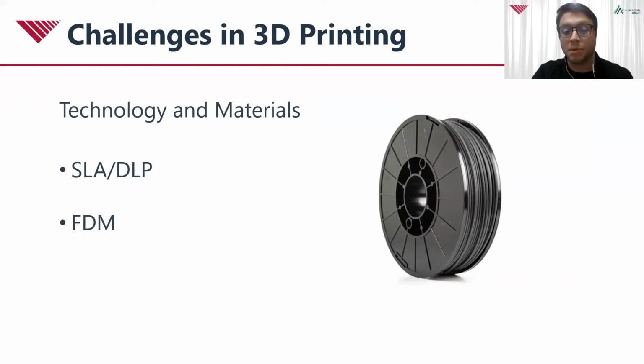With FDM, there is a wider choice of materials, and compared to other technologies, it can offer the quickest turnaround for a printed device. Some FDM materials can be reheated in localized areas to make adjustments for fitting. However, with FDM-based materials, you do need to be more careful with shape overhangs. And in many cases, you'll need to design in some supports or scaffolding to support the shape as it's being printed. You also have to be careful that you're getting sufficient interlayer adhesion. Otherwise, you'll increase the likelihood of failed prints or weak points in your final device.